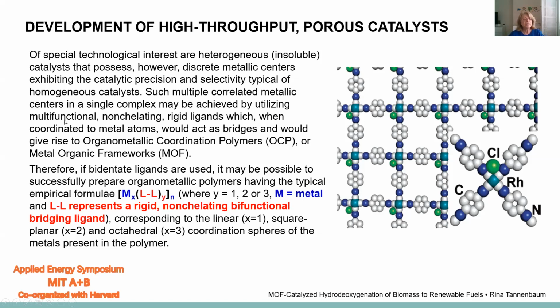This can be achieved by utilizing multifunctional, non-chelating ligands. That means that if you have a ligand that has two or more functional groups at the end, it will be a rigid ligand, and so it will bond to two different metallic centers, and it's not going to self-bond to a single metallic center to form a loop. And so if we have these non-chelating rigid ligands that, when coordinated to metal atoms, would act as bridges, they would give rise to organometallic coordination polymers. This is what it was called in the 80s and 90s, or metal organic framework, which is what it is called nowadays, with the revival of this area of chemistry.